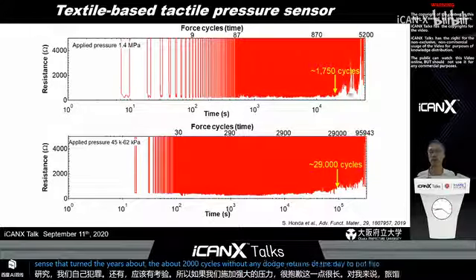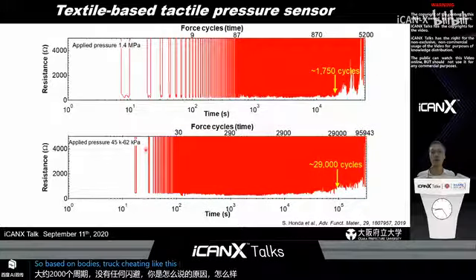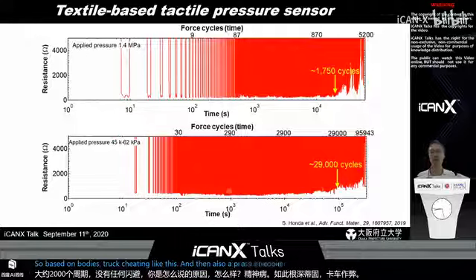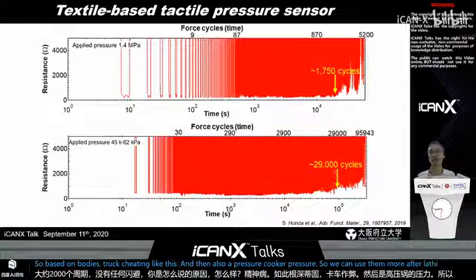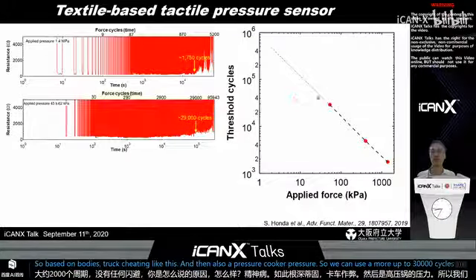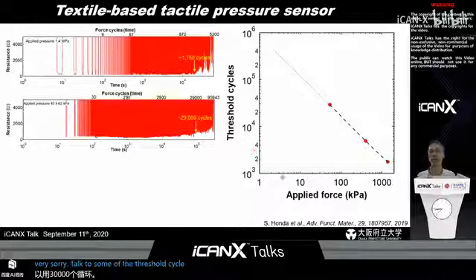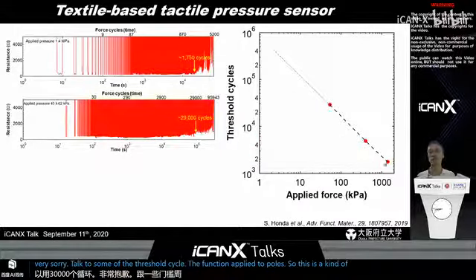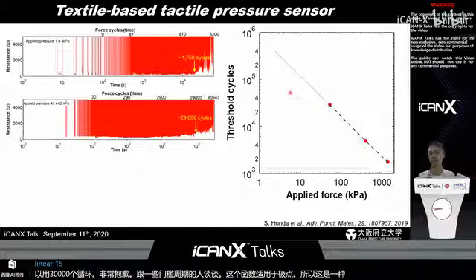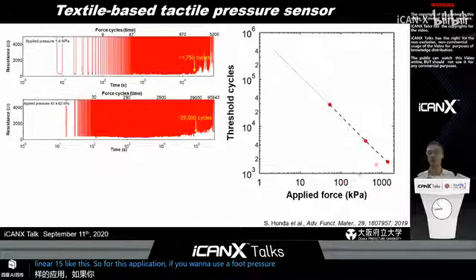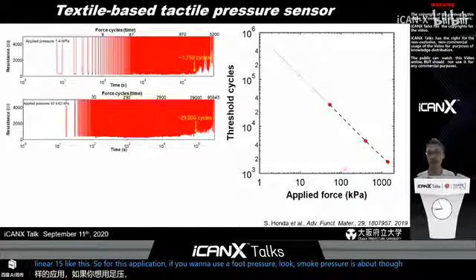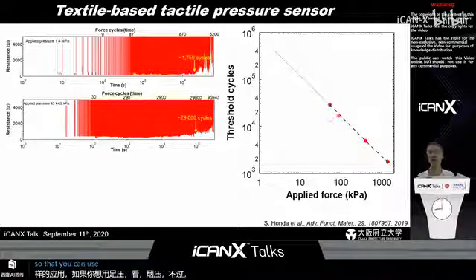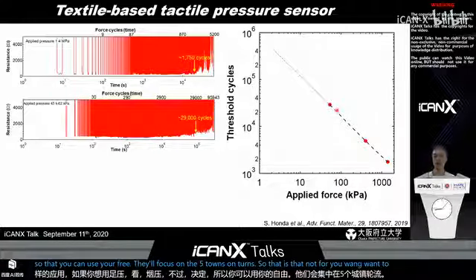However, after 2,000 cycles, the resistance value is fluctuating like this. At a lower applied pressure, we can use it up to roughly 30,000 cycles. Then we plot the threshold cycle as a function of the applied force. This is on a log scale, but it is a linear fitting like this. For foot pressure monitoring, the maximum pressure is about in this region, so you can use it roughly 4,000 or 5,000 times. That is roughly 1 or 2 days of use if you apply this sensor on your shoes.